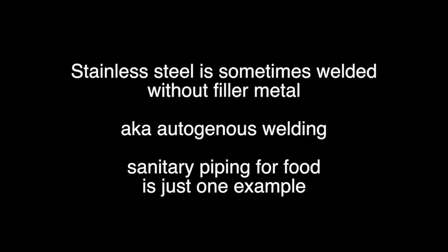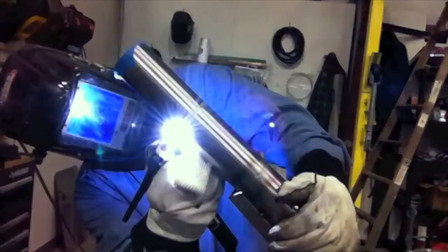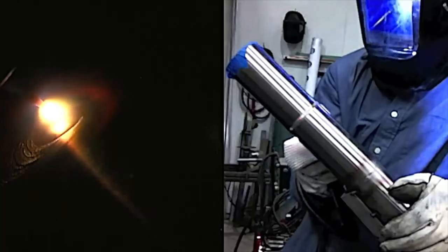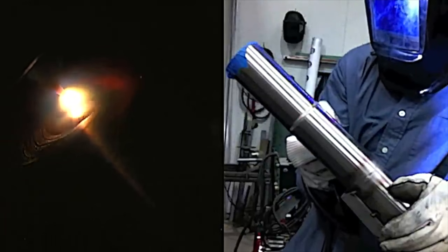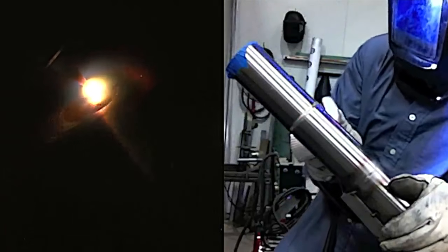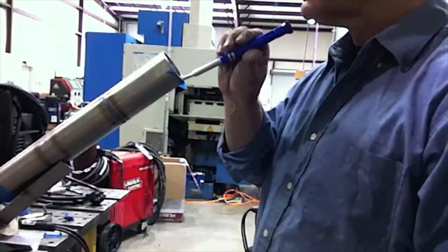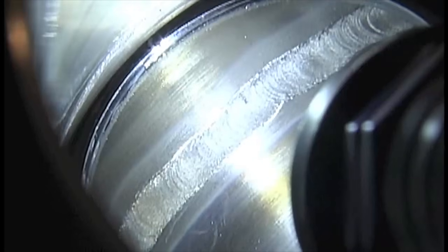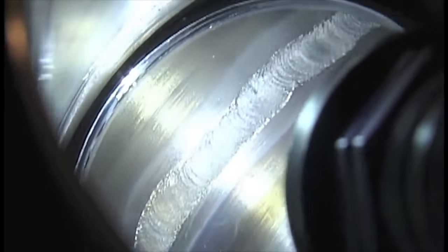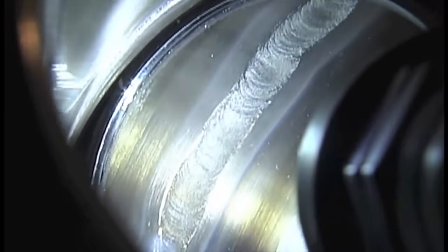Sometimes stainless steel is welded without filler metal. That's also called autogenous welding. A good example of that is sanitary tubing like this, where it's welded without filler metal. And the main concern is a purge on the inside, an argon purge, so that the weld metal is silver and there's no crispy critters in there that can grow bacteria.